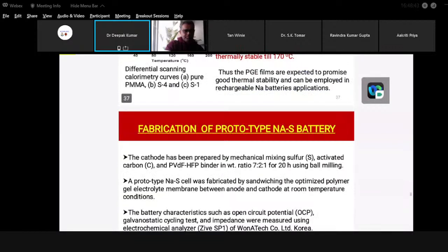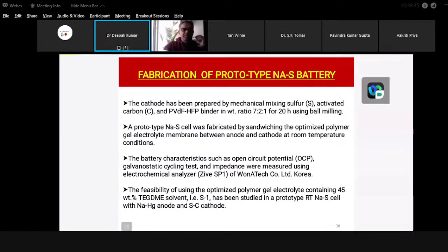The fabrication of prototype sodium-sulfur batteries. The prototype sodium-sulfur batteries have been made using PVDF-HFP as a binder element, sulfur as the main component, and activated carbon is also utilized. The prototype is made by sandwiching the optimized electrolyte between anode and cathode, and for the anode, NaHg was utilized. We have performed the battery characterization by measuring the open circuit voltage, galvanostatic cycling testing, and impedance measurements using an electrochemical analyzer, Zive SP1.